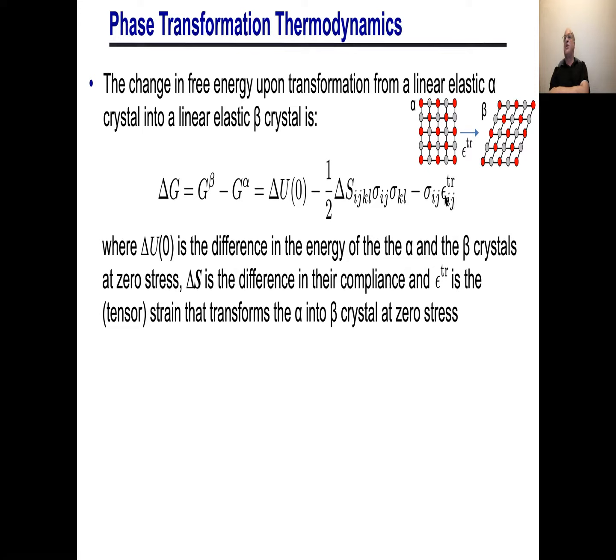And sigma ij, epsilon ij, tr is just the stress you apply in a product with the transformation strain. And this transformation strain is a stress-free strain that takes you from the alpha phase into the beta phase. Okay, so we can do that just by crystallography. Okay, so that's the transformation strain. And again, this is still linear elastic.